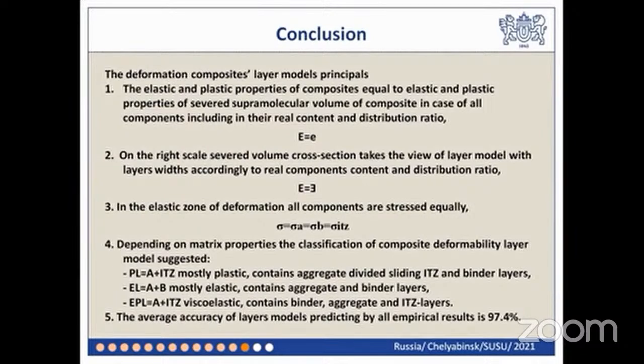PL module is useful for viscoelastic or plastic deformation of composites when ITZ plays a matrix role. EL module is useful for composites with ITZ properties near or equal to binder properties. EPL module is useful for complex composites with weakened ITZ.